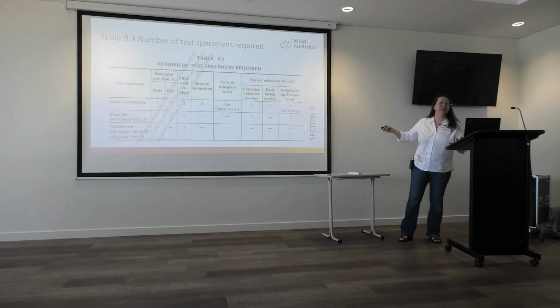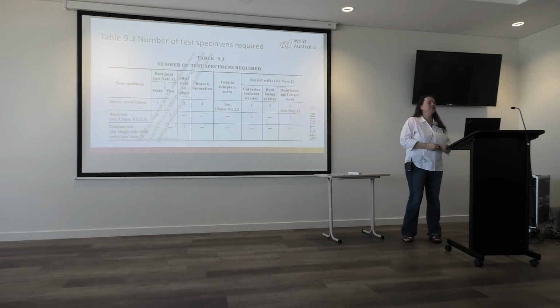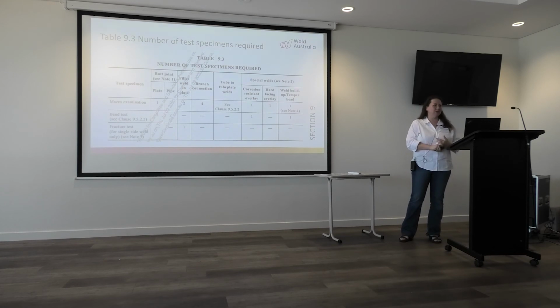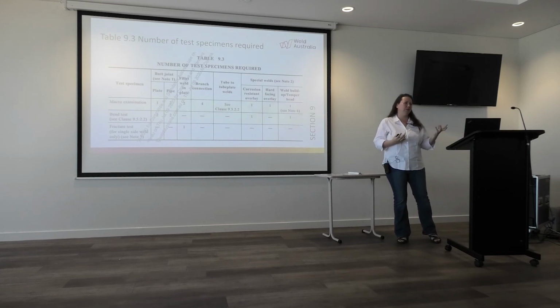But I want to get to this table because this is the part where we had 2 negative comments from people requiring that you do bend tests for gas metal arc welding and flux core arc welding. And we've had 2 comments coming back saying, oh, this is going to kill industry to get a welder to do a bend test with flux core and with MIG welding, gas metal arc welding. And almost every other person in, for example, the seminar that I was running that was working in a test facility said that welders can pass the radiographic testing with MIG and flux core and they'll fail the bend test, which is why this requirement has been brought in. So if that answers your question, Neil.